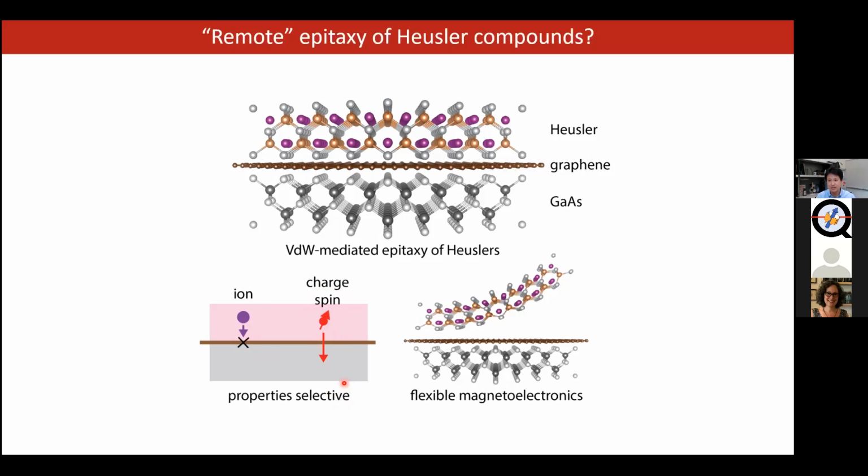And one of the major challenges is that these interfaces are inherently unstable. And so one thing that graphene brings is that it's a great solid state diffusion barrier that's been known for years. So it could block interdiffusion or ion transport across the interface. But ideally, because graphene is atomically thin and transport occurs via tunneling across that interface, this is a limit where this atomically thin diffusion barrier might be nominally quasi-transparent to the injection of charges and spins across this interface.